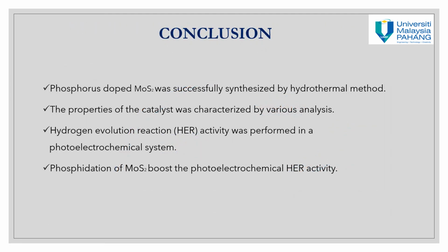In conclusion, the phosphorus doped MoS2 was successfully synthesized by the hydrothermal method and then characterized by various analyses, and also tested in the PEC system to evaluate the hydrogen evolution reaction activity. The present work conveys that the phosphidation of MoS2 is able to boost the photoelectrochemical HER activity.